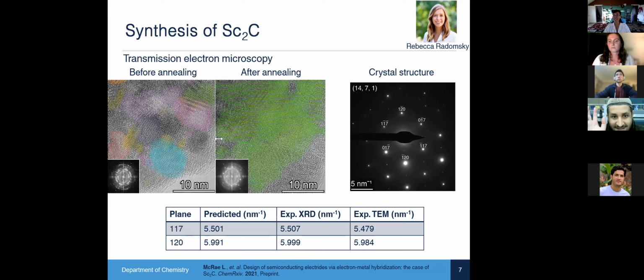Hey, I have a question. Can I ask? Regarding after annealing, there are different d-spacings. Do all these d-spacings belong to Sc2C or no? Yes, so all of these spacings do. The TEM comes from the electron diffraction patterns. The XRD comes from the X-ray diffraction patterns of the layered scandium carbide, and predicted again comes from the layered scandium carbide that we predicted computationally.